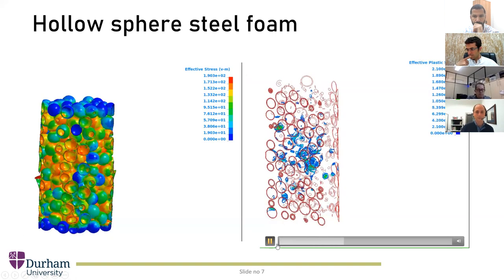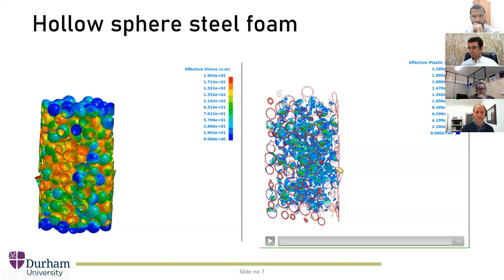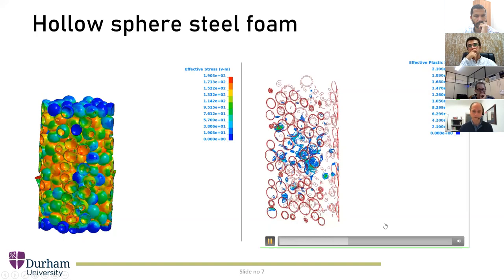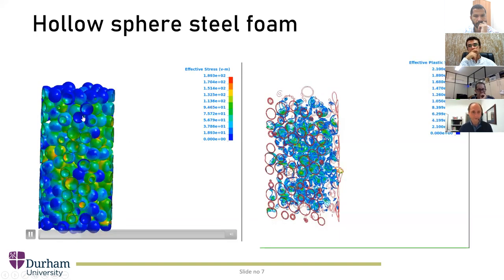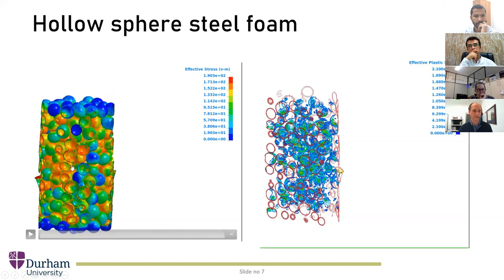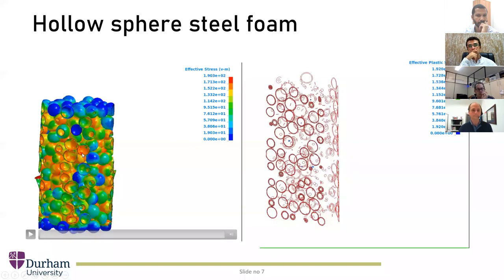But yes, looking at those theoretical analyses, it became apparent that if the shells are very thin and this was controlled by elastic buckling, maybe we could have a reversible mechanism and the Young modulus would control the response. And I think we managed to find a paper on ultra thin lattices, tubular ones, but they have a very similar buckling description, which were reported to be hyperelastic. And so that was a good observation there. But I guess this is the platform material, flexible, crushable, and that is useful.